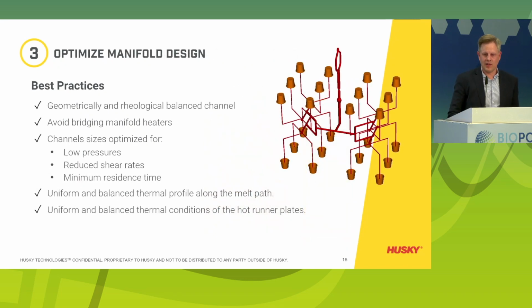Optimize the manifold system is that Husky geometrically and rheologically balance all the hot runner systems based on low pressures, reduce shear rates, minimum residence time. So that is what we do for each system prior to shipping and manufacture. What we also recommend is to avoid bridging manifolds. Often, and this is common, you have a heater from the manifold on the injection side and clamp side, and they are bridged together. We recommend to not do that.